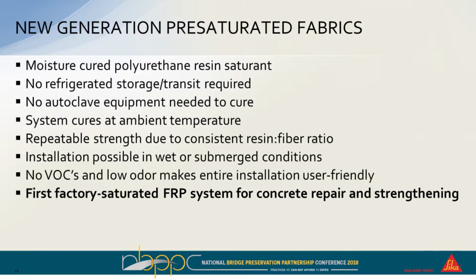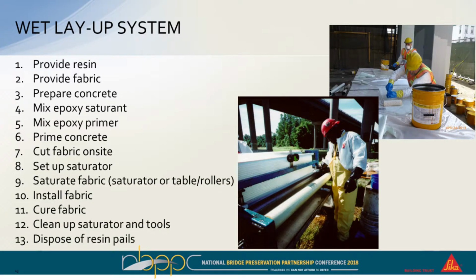Oftentimes with epoxies, you want to wait until the concrete has dried out so you get a better bond. Since this is a moisture-cured system, it actually will bond very well even to damp concrete. Little to low VOCs, and low odor makes them user-friendly. And also the fact that this is the first factory saturated FRP system that's in use for concrete repair and strengthening.